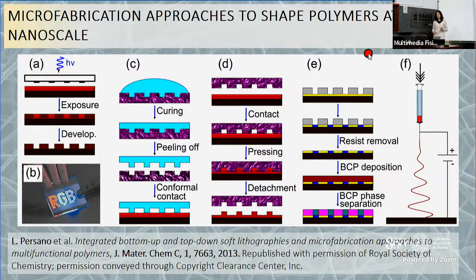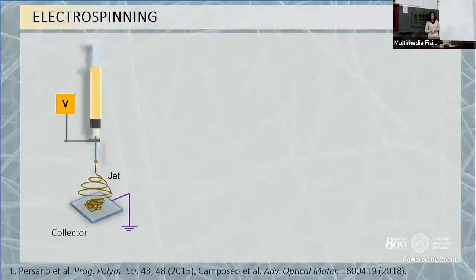The last technology is electrospinning, and this is the one I will talk about more in this talk today. So, this is, let me say, a quite easy technology. Why do I say easy? Because it is just based on the use of three key elements, which are a spinneret, a voltage bias generator, and a metallic collector. So you have a polymer solution that you feed at constant flow rate through the spinneret, and you apply a bias voltage between the needle of the spinneret and a metallic plate, which is named collector.